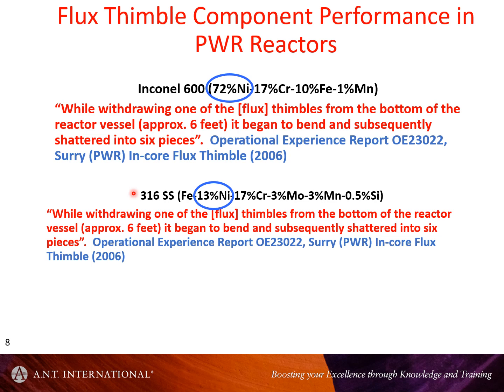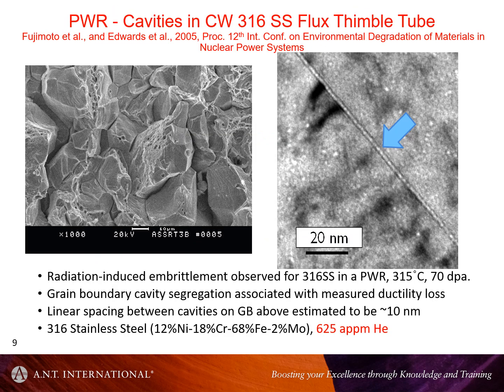More recently, in the 2000s, people have been studying 316 stainless steel, and it was found in the 316 stainless steel tube, this is some work by Fujimoto and Edwards. They actually did do some TEM, and they were able to show that there were bubbles concentrated along grain boundaries, and corresponding with that, there was some embrittlement, some intergranular failure.